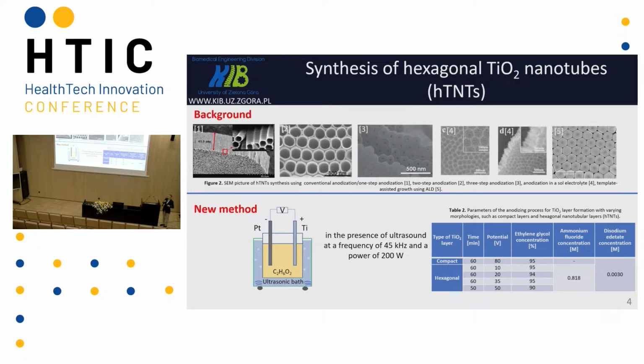When we got this idea to obtain hexagonal titanium dioxide nanotubes, we looked in the literature to see if somebody had done it before us. We found maybe not a lot, but a few papers where the hexagonal titanium nanotubes were described as circular nanotubes, but in hexagonal arrangement. And only a few, to be exact 5 papers, show the possibility to form hexagonal titanium nanotubes. And as you can see, the most uniform nanostructure was obtained using the atomic layer deposition method with alumina template.